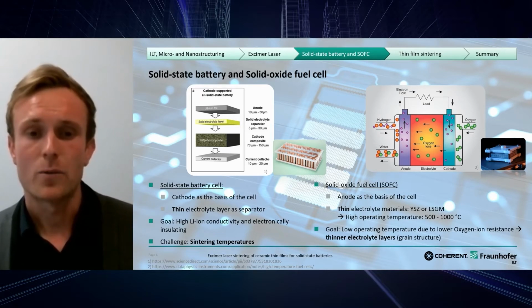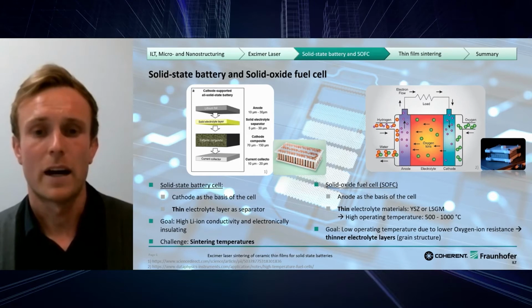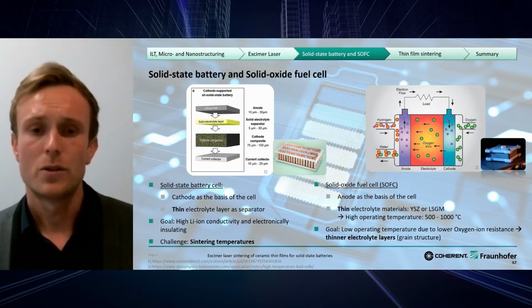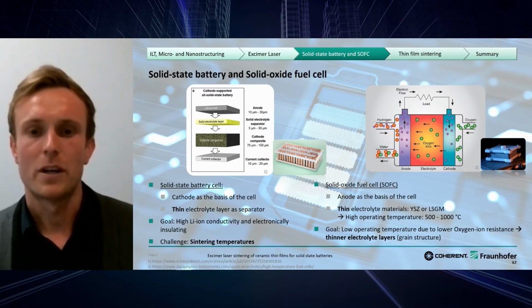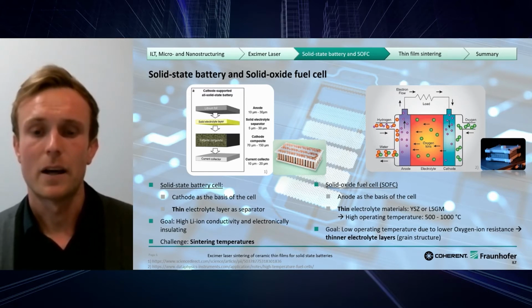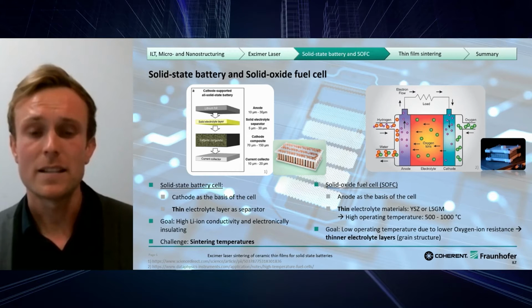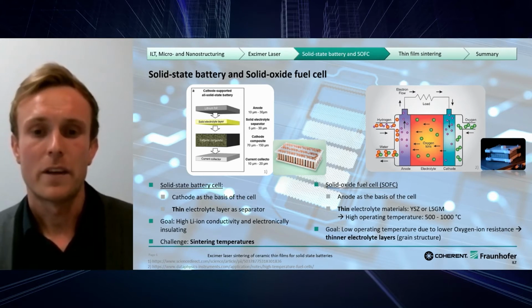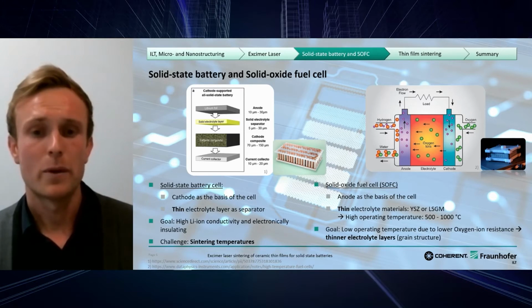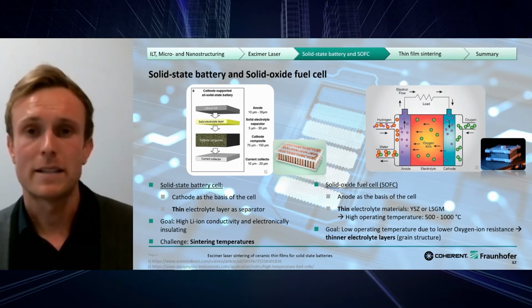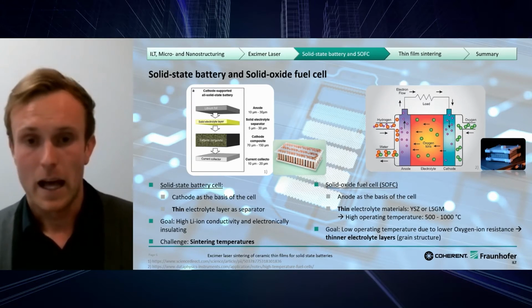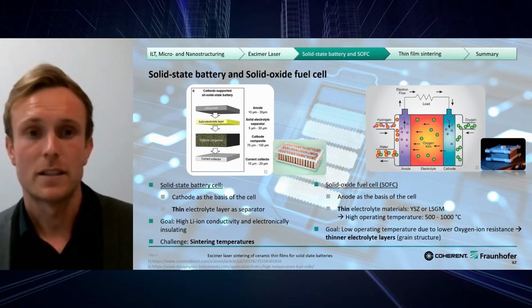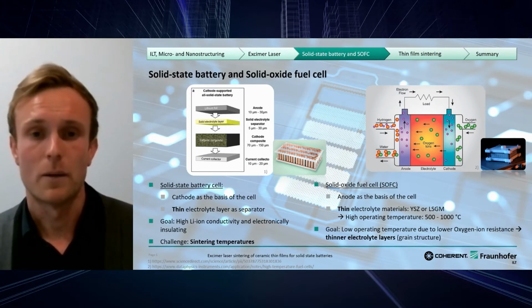But on the other hand, we have to operate the cell at higher operating temperatures. So one goal here is to reduce this operating temperature by reducing the oxygen ion resistance. And this can be achieved if the electrolyte layer gets thinner. And it would be good to maintain a grain structure, and so a sintering process is required as well.